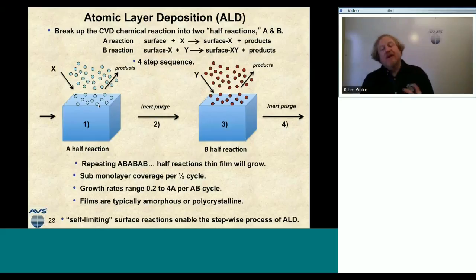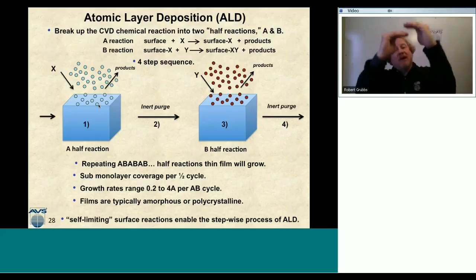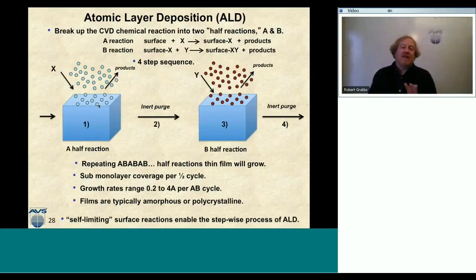cycle. So these films, because we're only growing partial monolayers at a time, are typically amorphous, or else they may convert into a polycrystalline form. So these films aren't single crystal, and they're grown at a much lower rate than putting down unit cell by unit cell. But really what makes this ALD chemistry work is the self-limiting surface reactions of this step that enables the stepwise process of ALD. So let's talk about that momentarily.